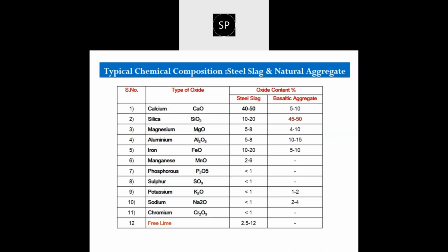In terms of the chemical composition, like how steel slag aggregate differs from the natural aggregate: the good quality natural aggregate obtained from igneous rock group like basalt and granite normally contains 5 to 10% calcium, while it is full of silica. The silica content is between 45 to 50%, and in case of steel slag, it will be devoid of silica, between 10 to 20%.